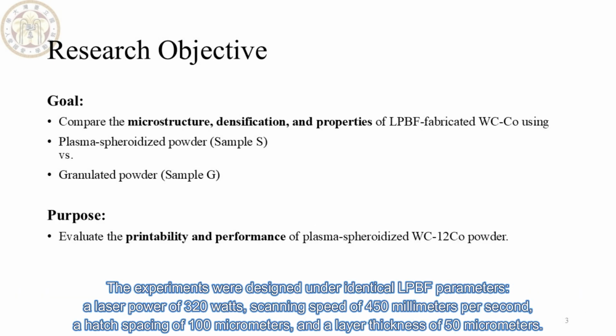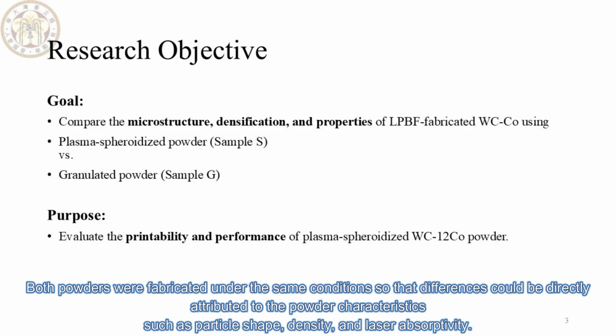The experiments were designed under identical LPBF parameters. A laser power of 320 watts, scanning speed of 450 mm per second, a hatch spacing of 100 micrometers, and a layer thickness of 50 micrometers. Both powders were fabricated under the same conditions so that differences could be directly attributed to the powder characteristics, such as particle shape, density, and laser absorptivity.